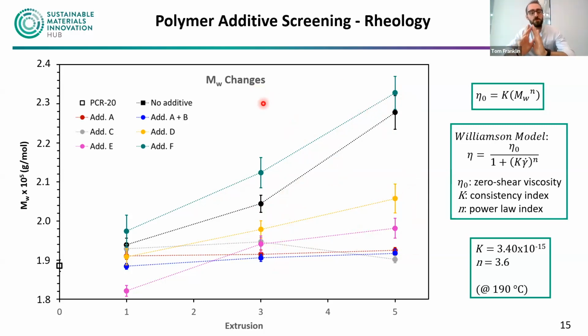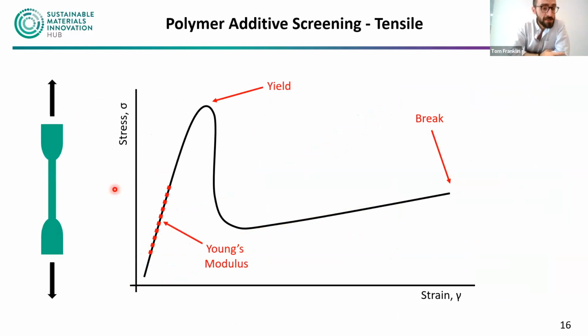As I've said, what we would expect to see in terms of the bulk mechanical properties is a difference, a change. What that change might be depends on the resin, on the test that we're doing. So we did some tensile testing, and essentially what we're doing is forming these little dog bone shaped molds and pulling them apart under quite high strain, and we get quite a lot of different bits of data just from this one test.